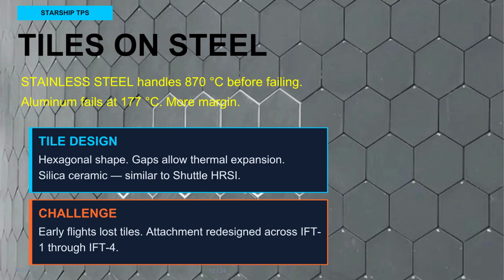SpaceX took an unusual approach with Starship: stainless steel structure, ceramic tile TPS. Stainless steel can withstand higher temperatures than aluminum before structural failure, roughly 870 degrees Celsius versus 177 degrees Celsius. That gives more margin before the tiles need to stop all the heat. The tiles are hexagonal, approximately 15 centimeters across, made from a silica-based ceramic similar to shuttle HRSI but manufactured differently. Gaps between tiles are intentional, they allow thermal expansion without cracking.